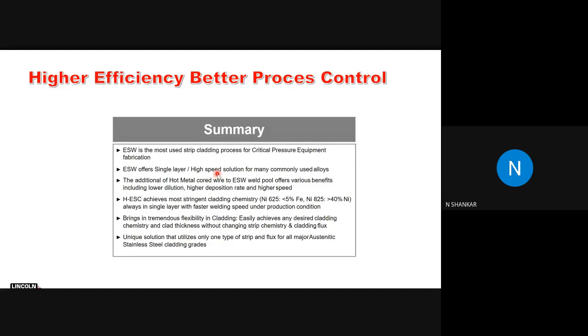ESW can offer you a single layer high speed solution for many commonly used alloys. By adding the hot metal core wire to the ESW weld pool, it offers various benefits including lower dilution, higher deposition rate, and higher speed. The hybrid ESC achieves much more stringent cladding chemistry, which makes it much better to use for these kinds of solutions. It gives you flexibility in cladding. It allows you to easily achieve your desired cladding chemistry and cladding thickness without changing the strip chemistry and cladding